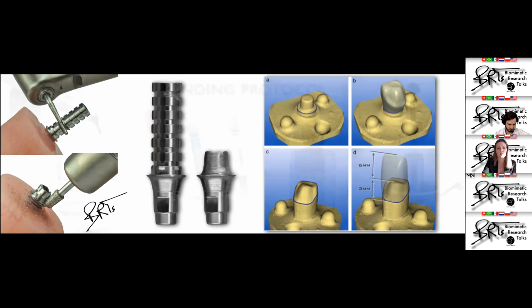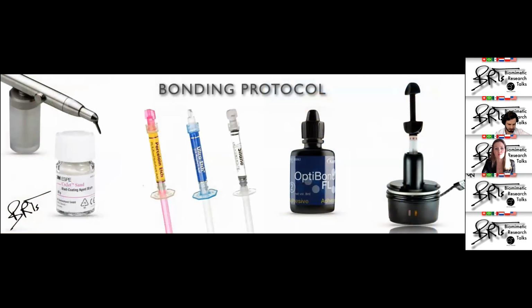So the bonding protocol followed the same sequence. We used sandblasting with CoJet on all the adhesive surfaces, and then we cleaned, using an ultrasound bath for 2 and a half minutes, and then we etched the porcelain, the glass ceramic, and cleaned again, using ultrasound bath again, and then we silanated, letting the silane evaporate for more than 5 minutes. We used Optibond FL as adhesive agent and preheated Z100 to bond those parts together.